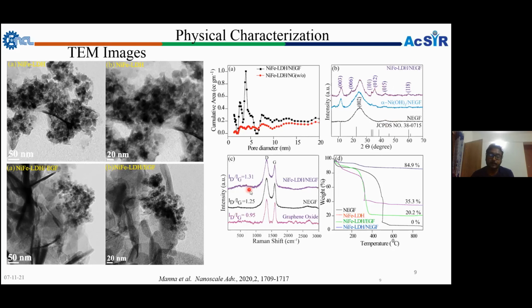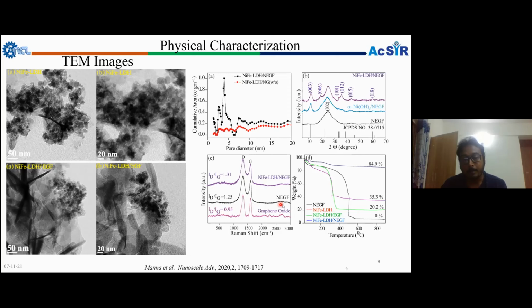We also did Raman analysis, as we are using a graphitic carbon like graphene oxide as a substrate. For graphene oxide we checked the Raman ID by IG value, where ID is the defect and G is the graphitic. The ID by IG value, meaning the defect in the graphene nature, is around 0.95. But when we apply the freeze drying method and form the nitrogen doped entangled graphene, the ID by IG value is around 1.25. So you can see a change from 0.95 to 1.25.